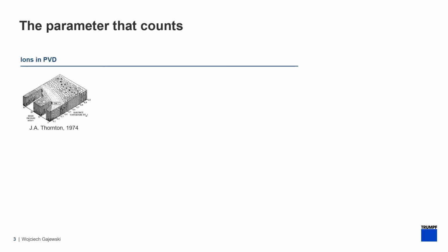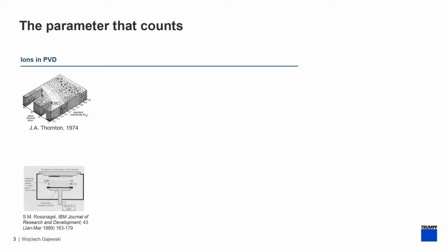However, there are applications where we cannot control the ion energy simply by changing the pressure. A good example for it is the semiconductor industry, where already in the 90s it was shown that to go with the smaller and smaller size of the structure produced on the silicon wafer, the ionization and the density of the plasma is a key factor.